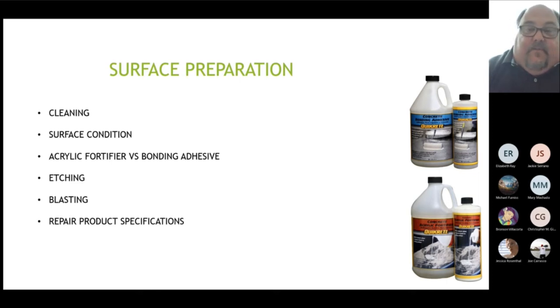So that's really important, especially if you have an old slab that's really porous. Even though it doesn't look like it absorbs a lot of water, when you put the hose on it and water disappears, it's going somewhere. So that's an example of that. You'd want to use that on patches that are either extremely porous or that are over 1 inch in depth. And the acrylic fortifier is an admix that you want to add to the concrete mix or to the patching product. That's like steroids for it. It just amplifies the adhesion, water resistance, helps with the cure, and that's for 1 inch or less.